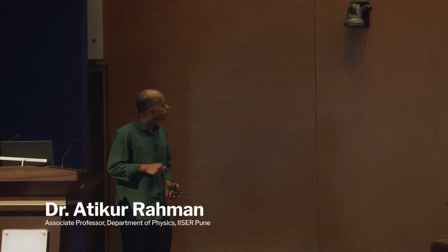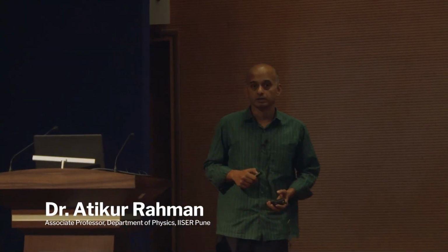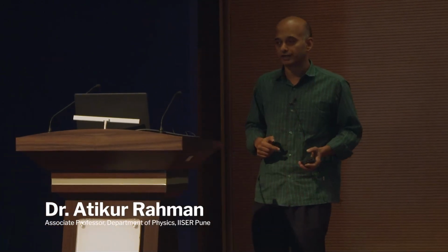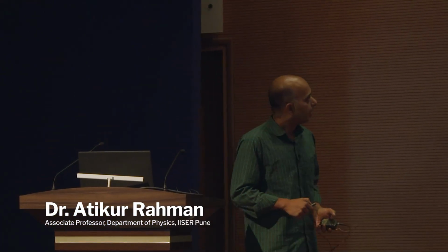So this is one bismuth oxyselenide, this is few layer. These are not van der Waals materials, these are non-van der Waals. But the advantage is that this is very stable, as it's basically Bi2O2Se, an oxychalcogenide. So once you grow them, it's perfectly fine. The advantage is that it has a very high mobility, so people are getting very interested. I think it was discovered in 2017 or 2019, not too long ago. And the mobility seems to have gone beyond 1 million or something.